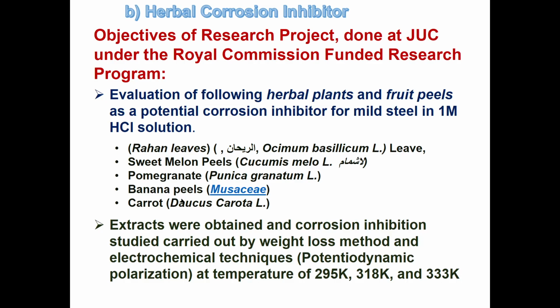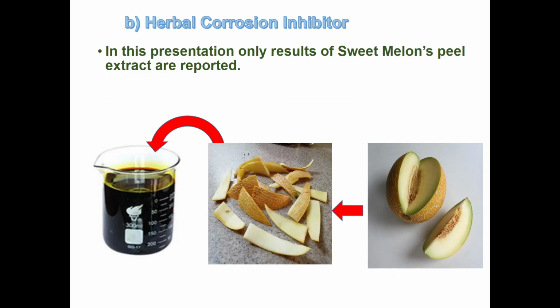In this study, what I am presenting is the effect of this inhibitor on the mild steel in 1 M HCl solution. We utilize various materials, including the rehan leaves, sweet melon peel, pomegranate, the skin of the fruits, banana peels, carrot, and many other materials. These extracts were obtained, and then corrosion inhibition studies were carried out on the material by weight loss method and the electrochemical techniques, which is also called potentiodynamic polarization, at different temperatures and at different concentrations of the inhibitors.